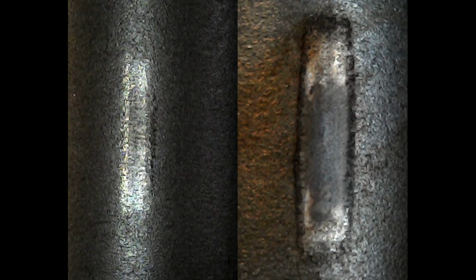400,000 fatigue cycles. Comparing the two rolling element test specimens, the grease used for the right-hand test resulted in much more wear and fretting than that for the left-hand test, with significant evidence of a build-up in oxide debris.